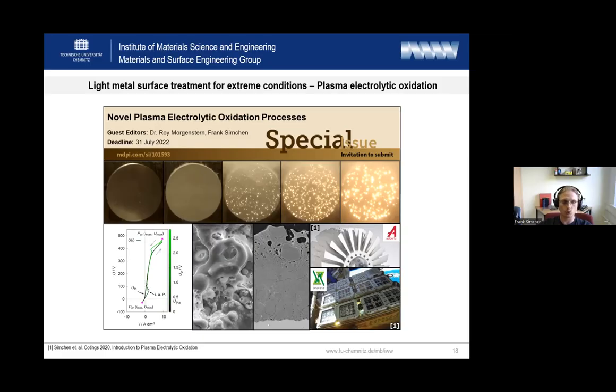And I'm not sure if the question was motivated in this direction, especially when you transport such etching gases which don't need to be contaminated by any component. It's also important that the coating doesn't release any gases. Yeah, this is also important for these optical devices which are shown there for space engineering. The ceramic coating doesn't release any gases. So the outgassing value, which is controlled in some challenging applications, is very, very low at PEO coatings. So you don't contaminate any optical devices by outgassing of the PEO. You don't contaminate your etching gases by use of this turbomolecular pump. And yeah, this is also one interesting aspect of this coating.